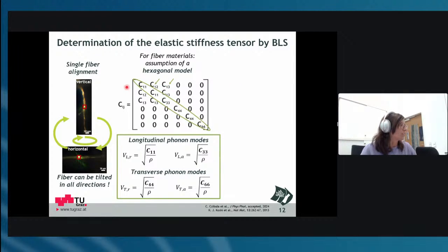But first, I want to show you here: C11 and C33 are basically longitudinal phonon modes, and you can determine them also with this second equation that I've showed you before. So here you use specific arrangements of the fiber. When I have the fiber in this alignment in 90 degrees, I can measure my C11. When I have it horizontally, I can measure my C33.